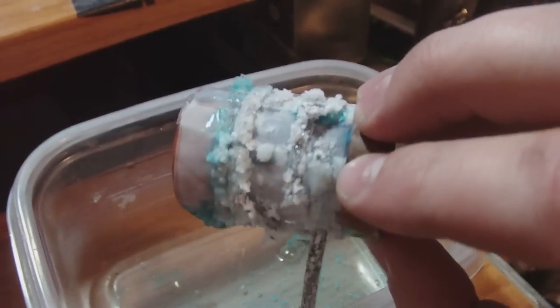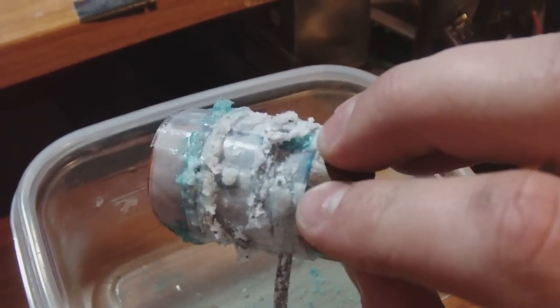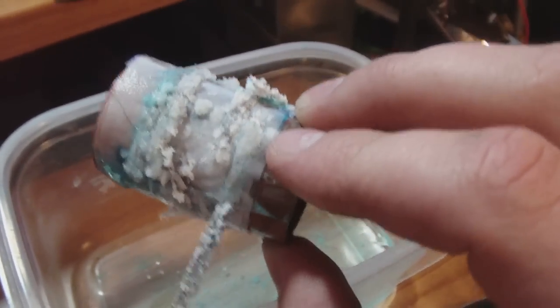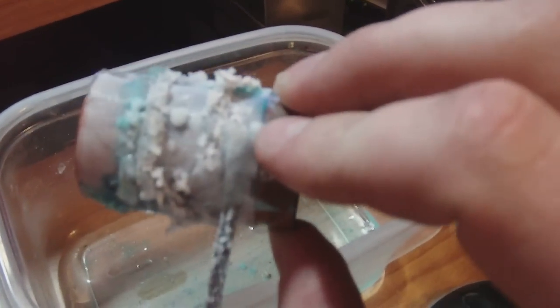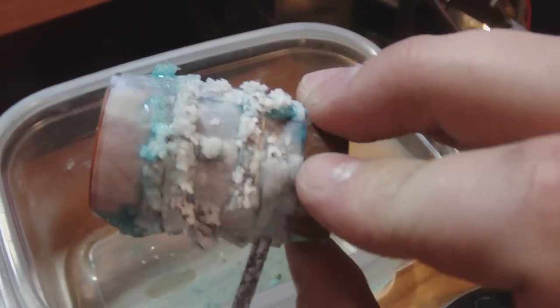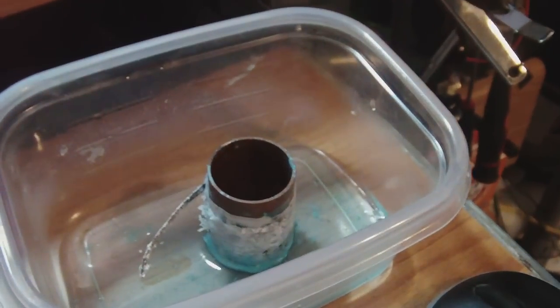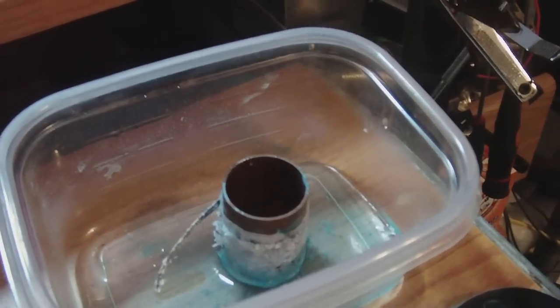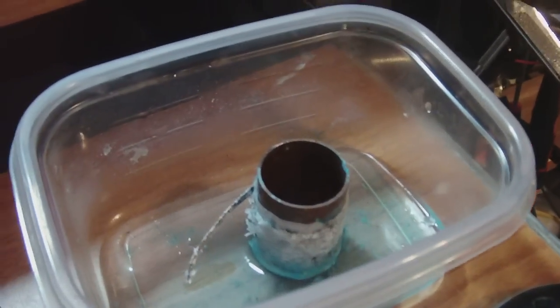This cell was never shorted out — it was just left in the water, closed up, to see what would happen. This thing is pretty old too. This is the worst case scenario for magnesium corroding, and you can see it's pretty bad. That white corrosion is what you want to stay away from. The black corrosion, I wouldn't say, is detrimental to the metal — you will have much less power, but it's not falling apart and flaking up and becoming a white powder. That's the biggest difference between the two cells. When magnesium corrodes to magnesium oxide, it becomes powder, the powder falls off, and the metal is destroyed. Magnesium oxide doesn't conduct really at all.